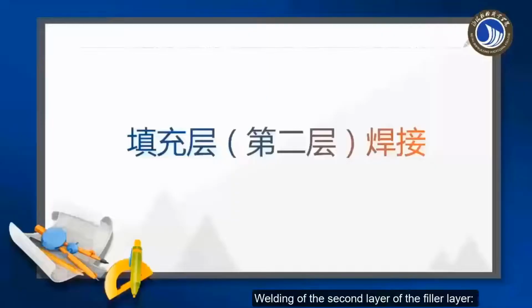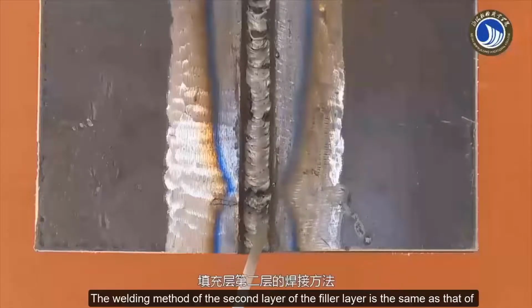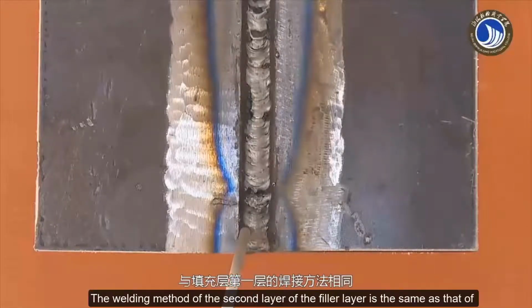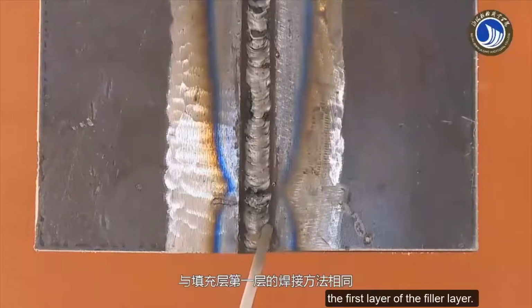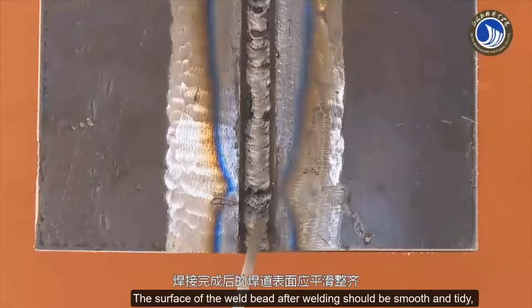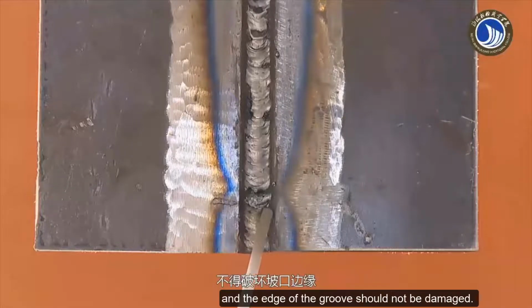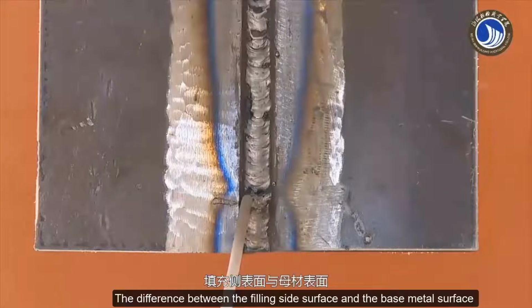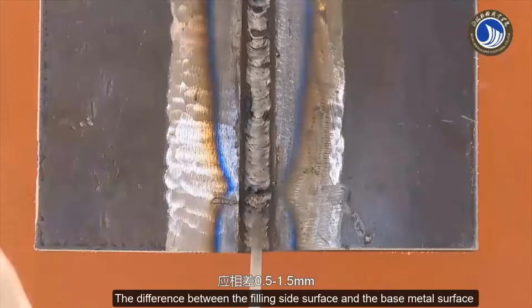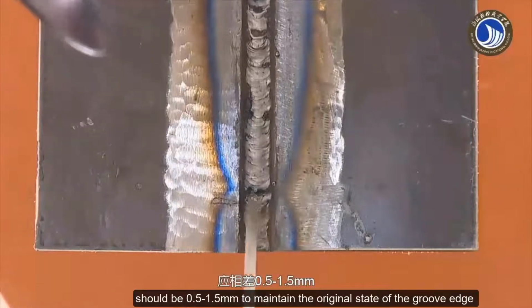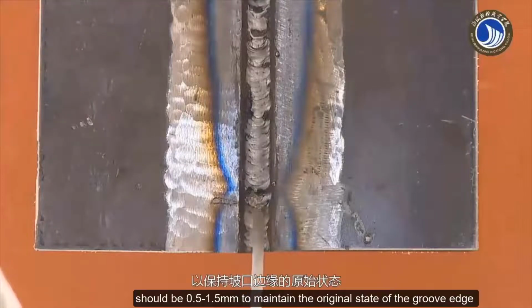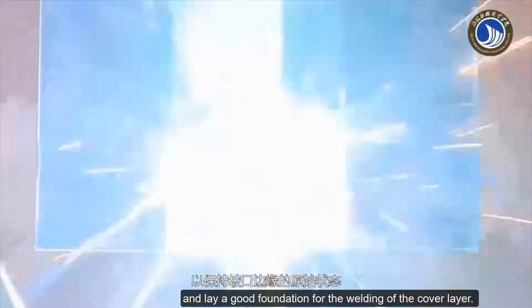Welding of the second layer of the filler layer. The welding method of the second layer of the filler layer is the same as that of the first layer of the filler layer. The surface of the weld bead after welding should be smooth and tidy, and the edge of the groove should not be damaged. The difference between the filling side surface and the base metal surface should be 0.5 to 1.5 mm to maintain the original state of the groove edge and lay a good foundation for the welding of the cover layer.